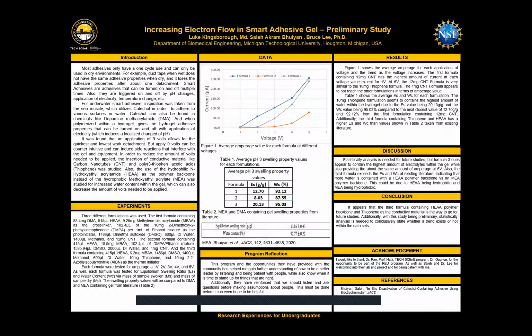Table 1 shows the average pH 3 swelling properties for each formulation. And this shows that the thiophene formulation was actually able to contain the most amount of water at 95% water content with a swelling ratio of 20, which is markedly higher than the literature equilibrium swelling ratio and water content. However, further statistical analysis is needed to actually conclude whether it is higher. It just appears to be higher at this point.